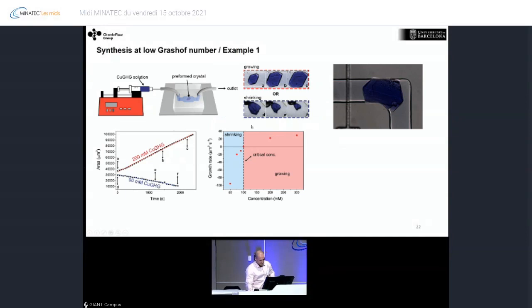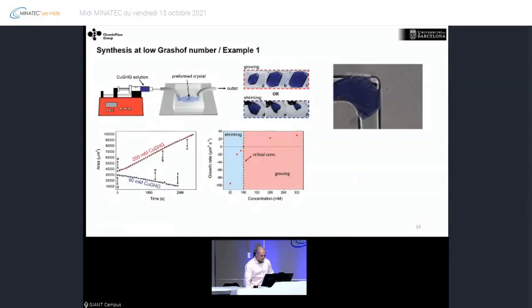So what we can do, as you see, is if we work above this 100 millimolar concentration, we can continuously grow the crystal. But if we are below this concentration, we can dissolve it. And this is what you see there. This is very, very interesting, because this is completely different to what we have in conventional laboratories. There the crystal will grow, as I said, following the crystallographic information. And we are not able to provide the crystal with new mass to grow as we want.